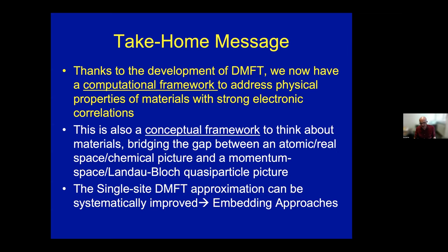So this phenomenon you cannot describe with single-site DMFT, and it is first and foremost to describe this phenomenon that cluster extensions of DMFT were invented. And what was shown is that by extending the range of the cluster to basically the correlation length or a little bit beyond, you can do a very good job at describing this phenomenon of the pseudogap, but you absolutely need this cluster extension for this part.